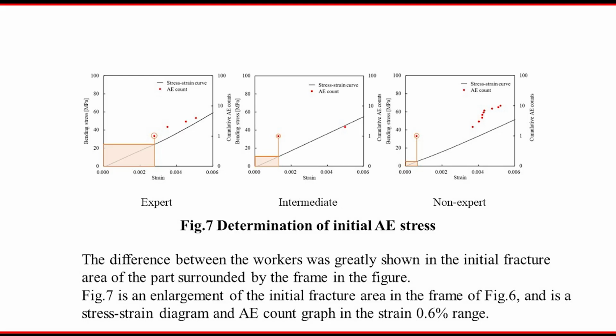So when we detect the first acoustic emission, the stress or strain of the expert is higher than the intermediate and non-expert. The first acoustic emission event indicates the initial fracture stress and initial fracture strain. So that means the initial fracture of the expert is larger than the intermediate and non-expert. Therefore, in the case of the non-expert, for example, when we apply the load, the initial fracture starts immediately from the beginning.